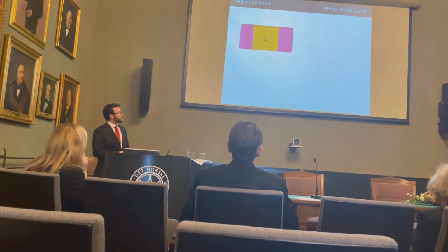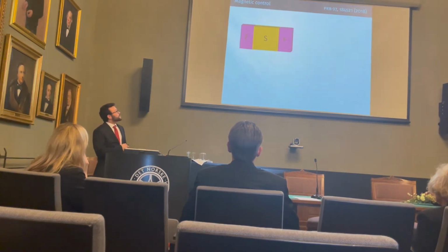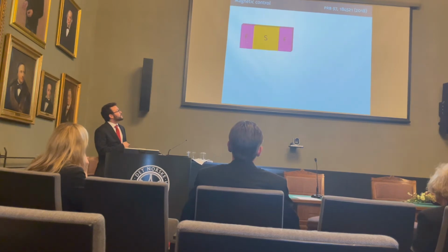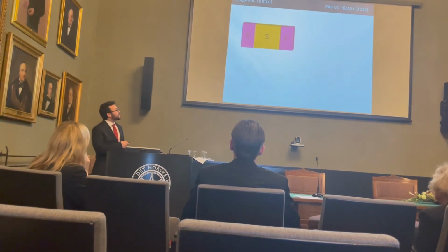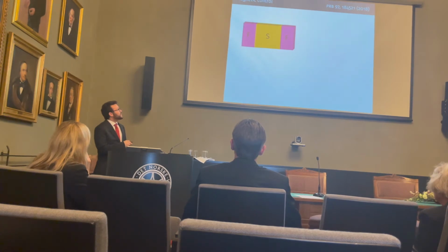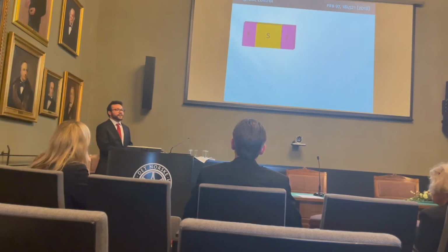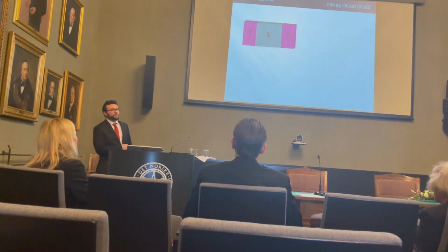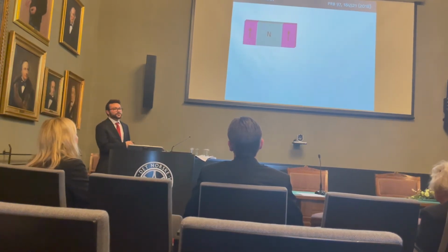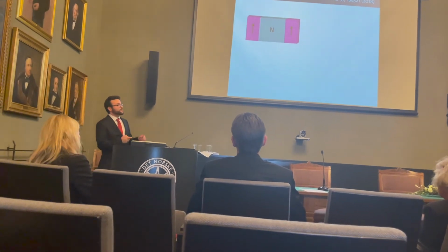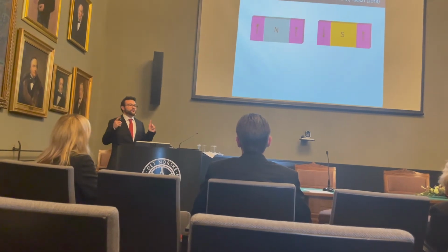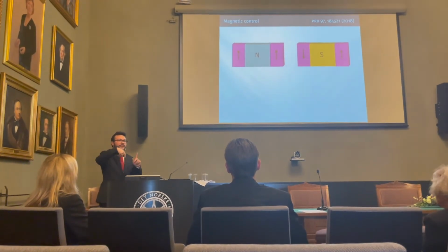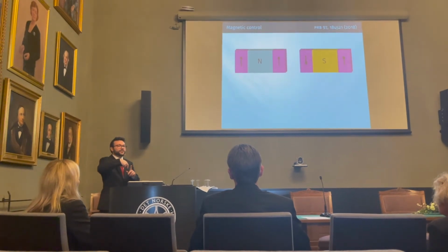First, just to give a brief background. If you take a superconductor and you place it between two ferromagnets, in this case the superconductor is supposed to be really thin, like 30 nanometers or something, then the ferromagnets might end up just killing all the superconducting properties entirely. So then the system looks more like this. The N here stands for non-superconducting or normal. However, if you manage to twist one of the magnets to point in the other direction, then the two magnetic fields cancel out near the center of the superconductor, and superconductivity is restored.